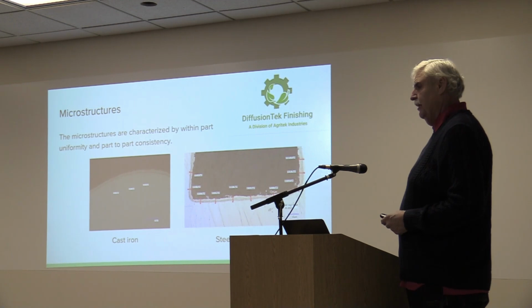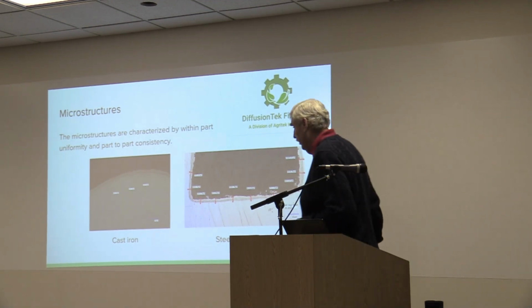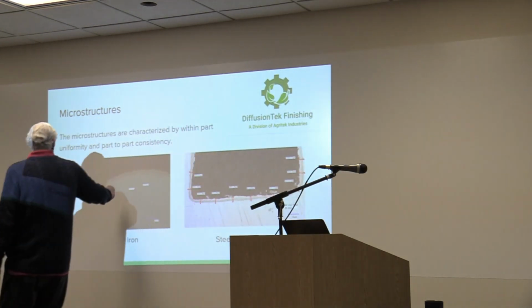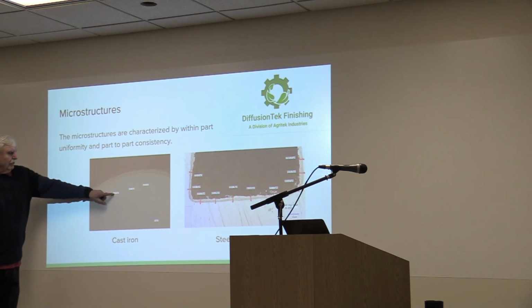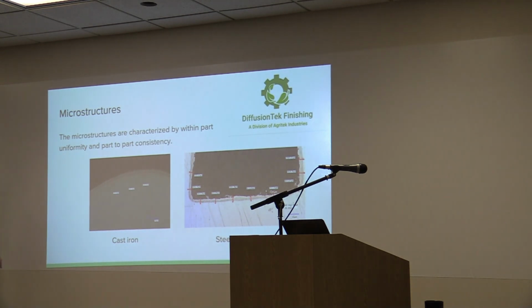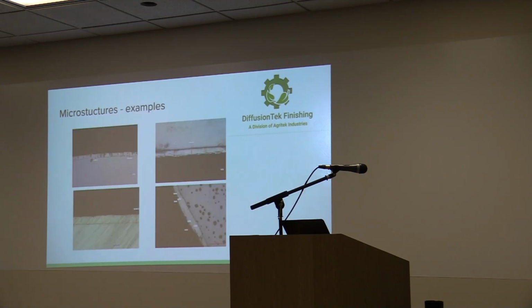Cast iron, and again, what it's showing is you can see the interface, and all these. I apologize for these. When you blow them up, it's difficult, but those are basically measuring the thickness. Oh, okay. And that's the same thing over there. It's interesting, the thickness inside the corners seems to be uniform. It doesn't gain thickness as it makes that 90-degree corner. It's because it's a vapor. It's not a plating or galvanized.